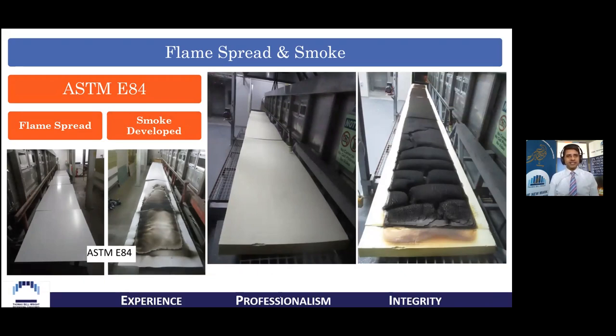So how this specific test works, the ASTM E84, is that it uses two reference materials, a calcium silicate board and red oak wood, to arrive at two reference points. The calcium silicate board has a flame spread index and a smoke developed index of 0. And on the other hand, you have the red oak wood, which has a flame spread index and a smoke developed index of 100. So if you imagine that when the red oak wood burns, the rate at which it burns and the amount of smoke it produces is 100-100.